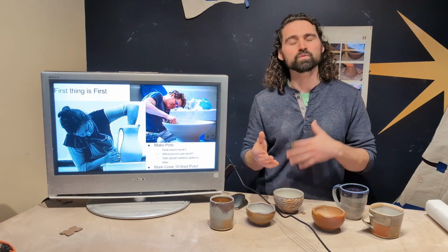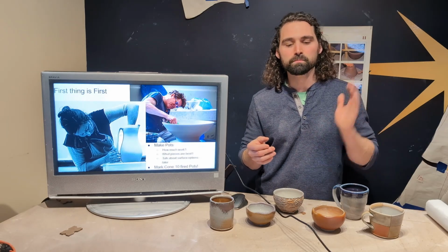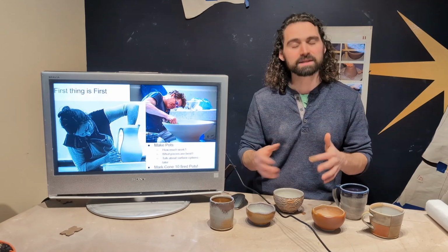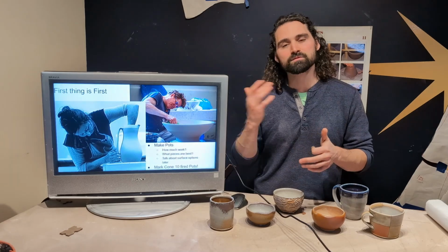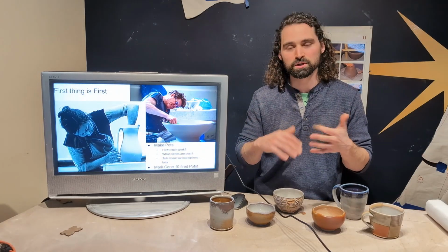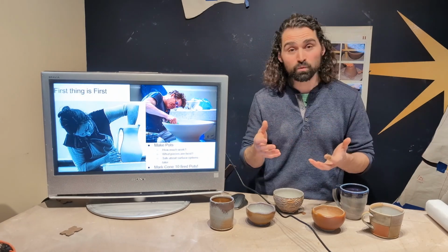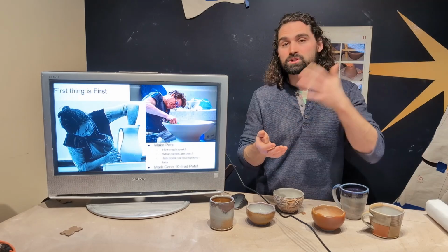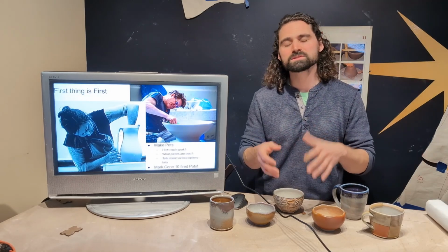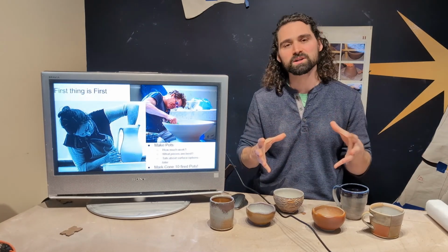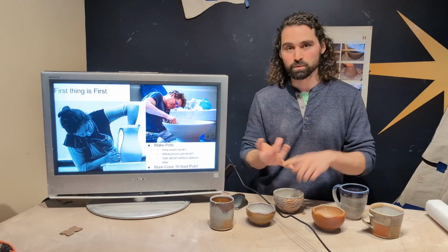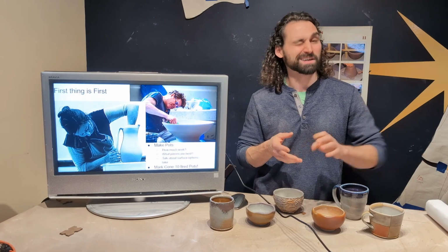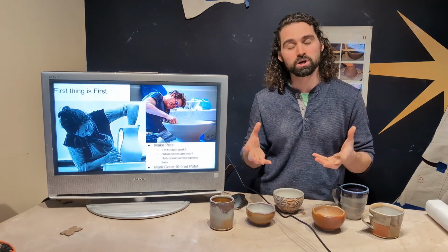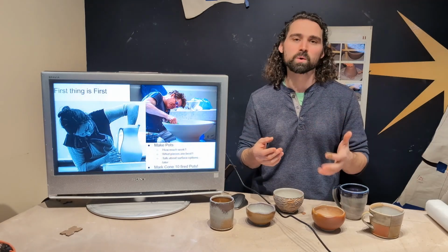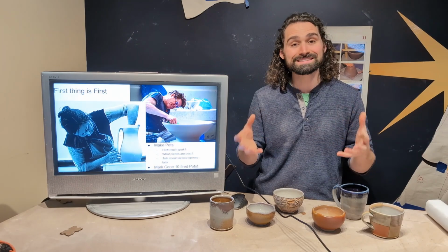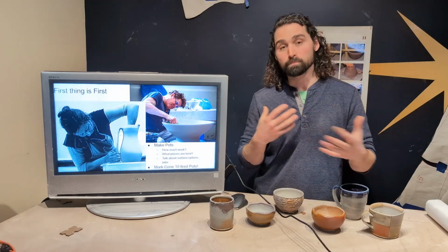The other thing that I really, really, really would urge you to do is to mark your cone 10 pieces differently than you normally mark your pieces if you have worked in lower fire work before. The reason being, if you fire something that fires to cone 6 even, into one of these cone 10 kilns, it's very likely that it will just melt into a puddle of molten glass. That ruins the shelf, it'll ruin the pieces around it, you're not going to make a lot of friends. Also you will likely be charged for that shelf, which are not cheap, because it's your responsibility to make sure that if you're using a different clay body than the ones we recommend, that you make sure that it's okay.